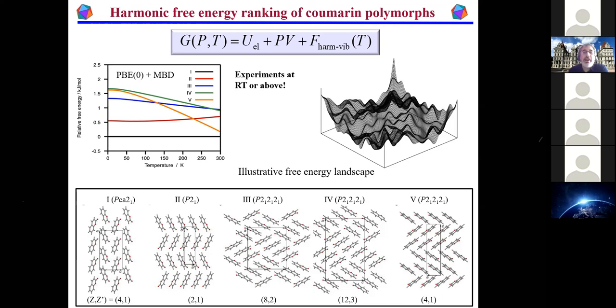which we were finally able to predict all of them using the simple protocol that I showed you way back with a force field. If you actually look at the harmonic free energy as a function of temperature, all right, so the ranking should be 1, 2, 3, 4, 5, and it turns out that for the force field we used, as you increase the temperature and apply the harmonic approximation, the ranking starts to go to hell at around 150 Kelvin. And as you approach room temperature, of course, things really go bad with the harmonic approximation. The ranking is lost, okay? And that's a failure of the harmonic approximation, and the quasi-harmonic approximation doesn't really do any better in this case, all right?